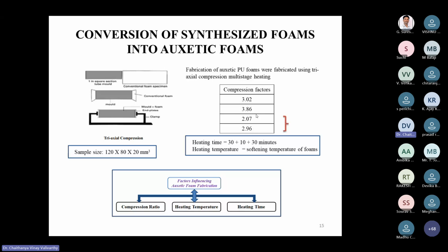And after taking this aluminum box with foam inside, we can put it in a heater and heat up to 200 to 250 degrees Celsius, which is also not standardized, because as I already mentioned, there is no standardization of making an auxetic foam. If we change one compound to make a PU foam, the properties will change. It won't change drastically, but there is a slight change in properties. So based on the compounds we are using, that's why we make our own foams instead of buying the PU foams from outside to make these auxetic foams.